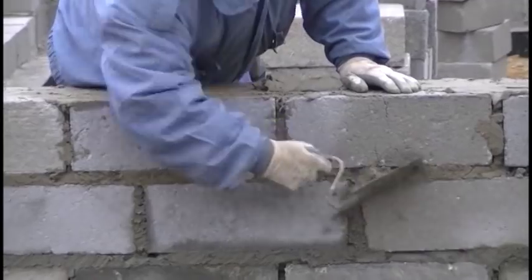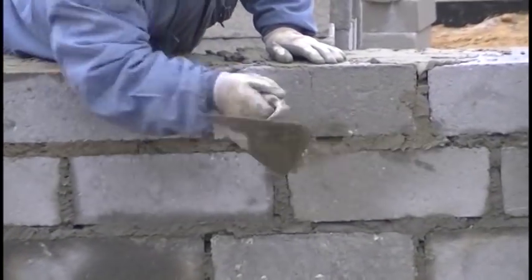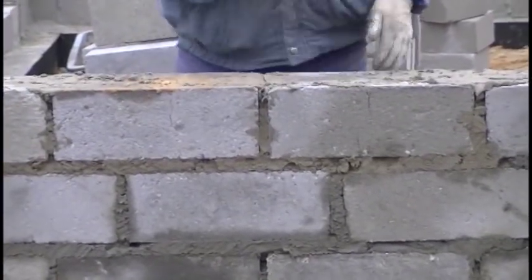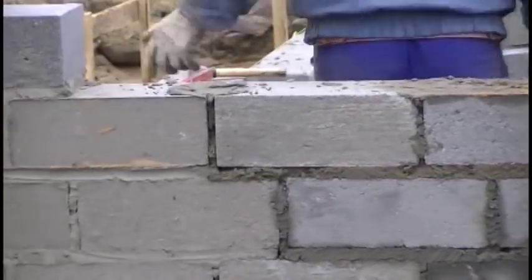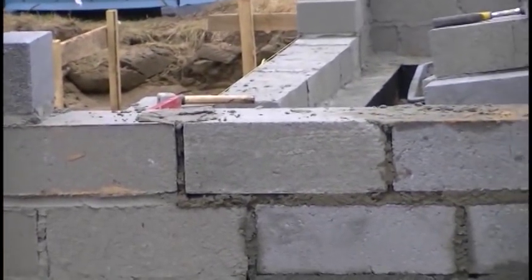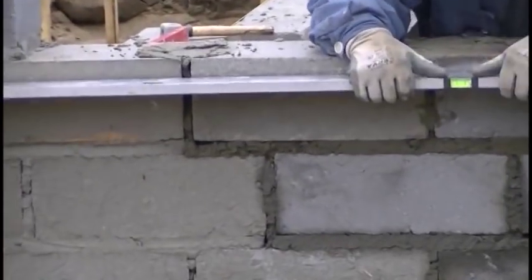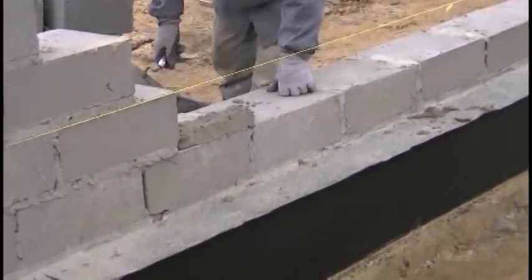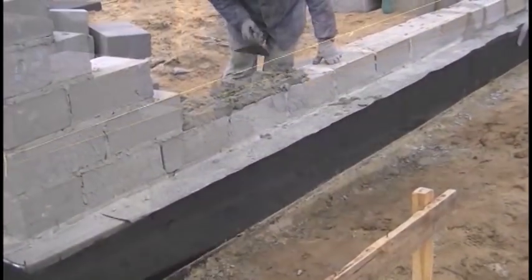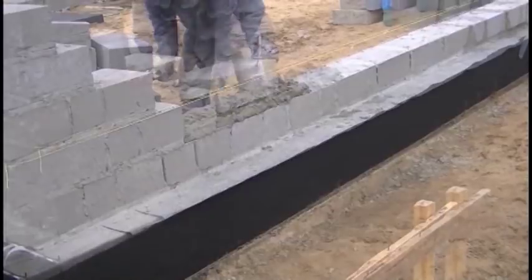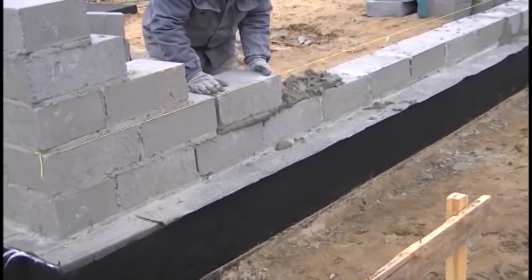Once on a building site, a foundation wall crack happened to me, caused by heavy equipment. Despite the fact that the wall had been drying for only 3 days, it broke in a thin straight line from top to bottom. The block wasn't spread as you would expect. Now let's go back to work.